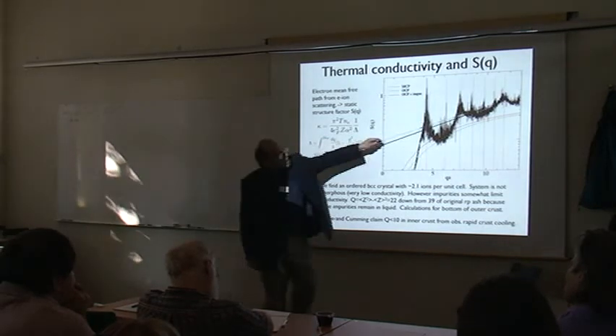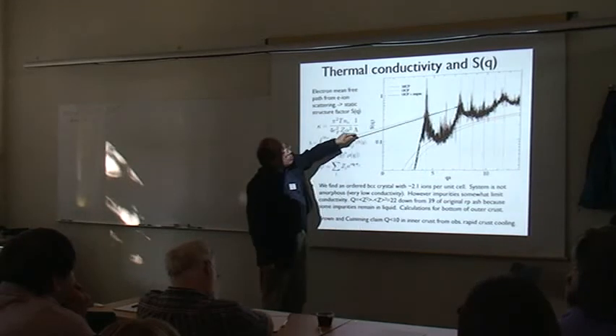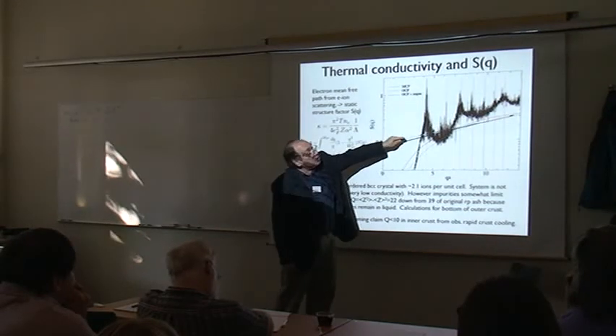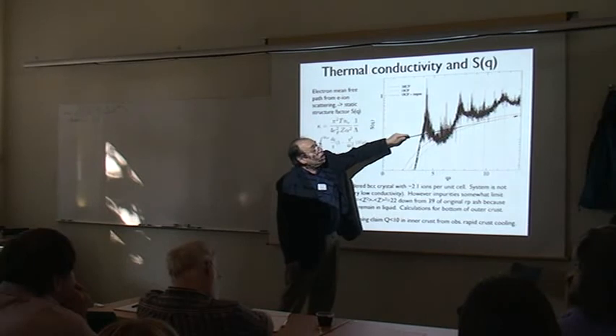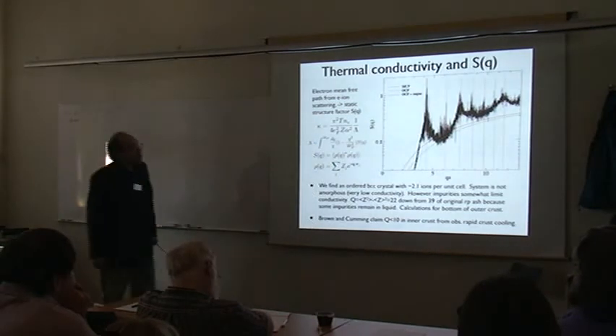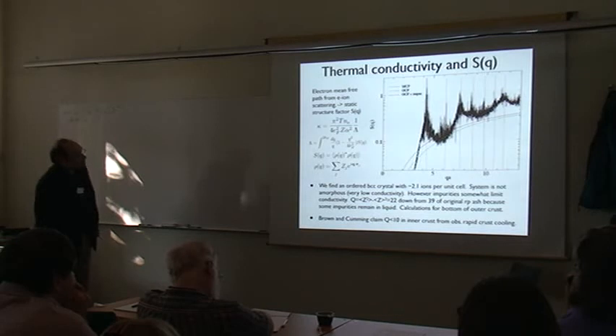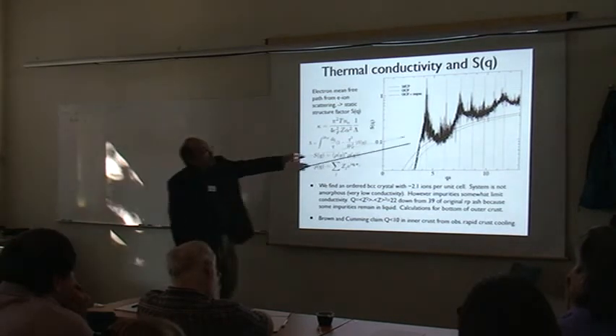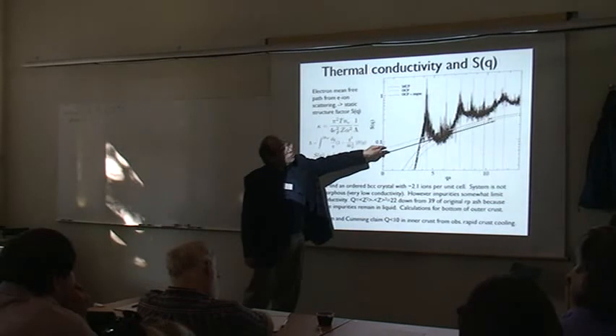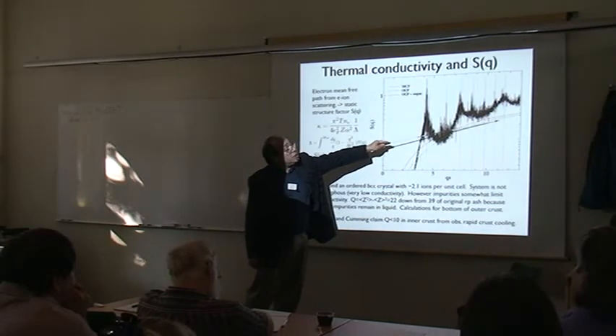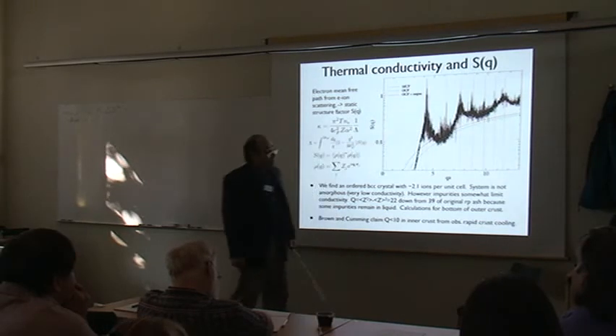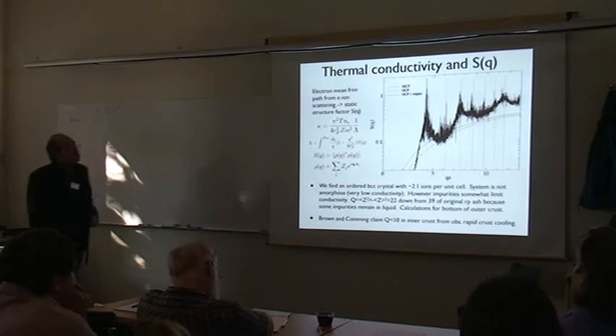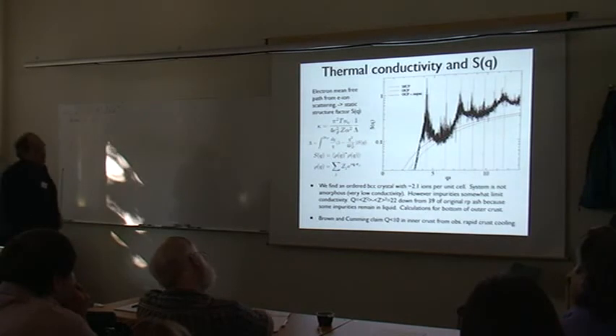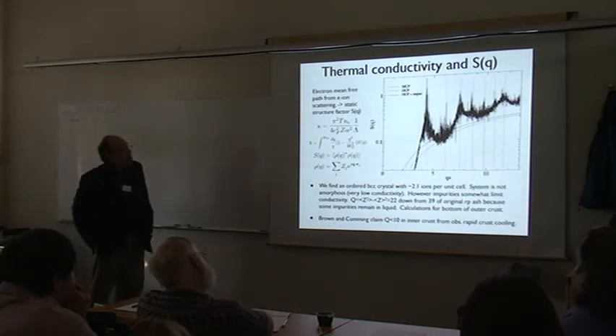And also you see that the black curve, it's a little bit noisy because of statistics, but it's significantly above what you'd get from the pure system. So you're seeing some effect from the impurity scattering. In fact, that effect is a little bigger: if the impurities were completely random and uncorrelated, they would take you from the green up to the red, but in fact they go higher. So there are important correlations between the impurities, and that enhances the scattering even more.